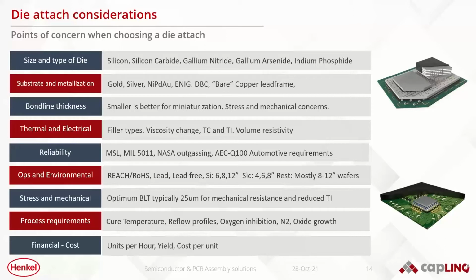Then the die may have a metallization level on it, and that metallization layer is ultimately the surface to which the die attach material has to adhere. Similarly, the substrate that it needs to adhere to is also an important consideration, to make sure that the chemistry and the die attach material selected has good high temperature die shear strength to those substrates: gold, silver, nickel, palladium, gold, and so forth.